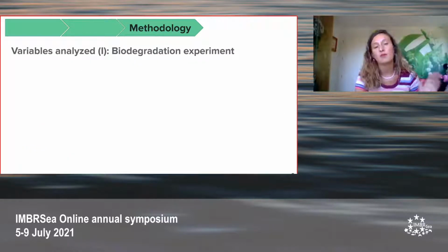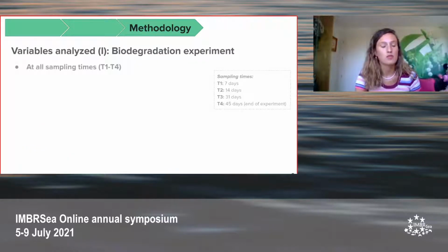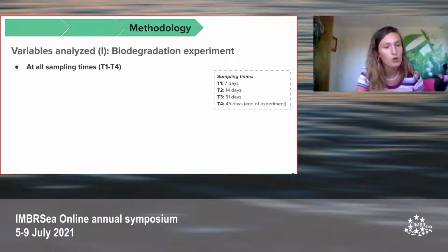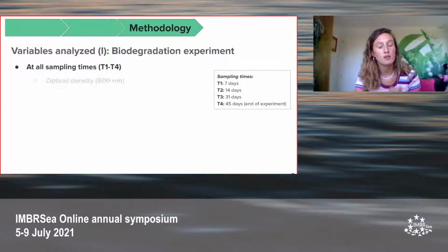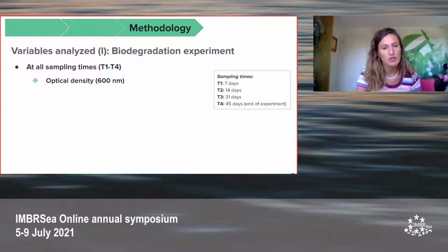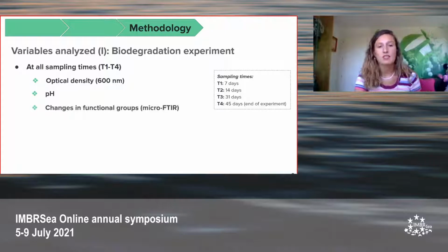Different variables were analyzed at all sampling times. So during the whole experiment, we measured the optical density to monitor the bacterial growth, as we were expecting a higher bacterial growth in the samples with inocula compared to the controls. We also measured the pH variations and the changes in the functional groups through FTIR.